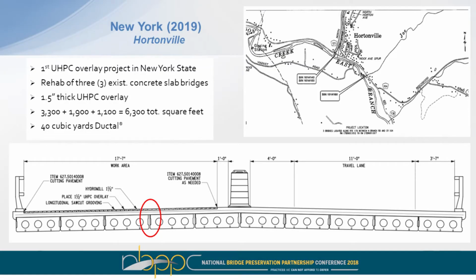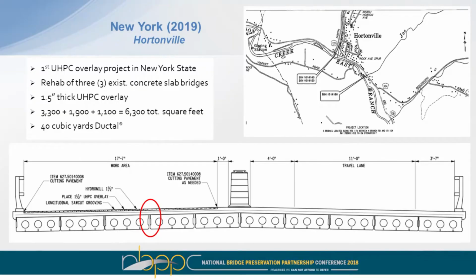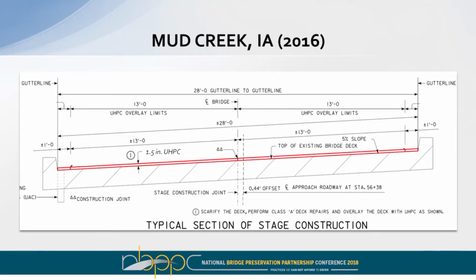Earlier this year, we did a 3-bridge package in New York State, down in the Hortonville area. Kind of a unique structure where they had these adjacent voided slabs, and they had seen some reflective cracking or the piano key effect, as we heard before. Their idea was, well, let's try to restitch everything together with a UHPC layer. So they went back and did about a 1.5 inch strengthening layer on top of that system. So this was the bridge in Iowa back in 2016, 1.5 inch removal and replacement.